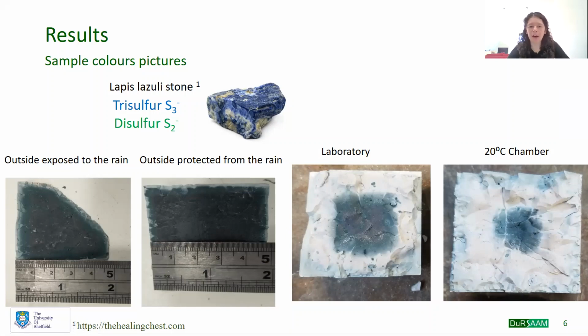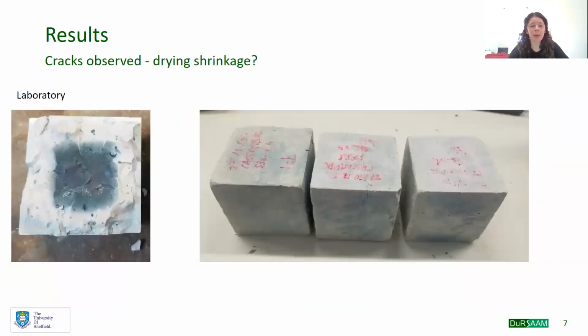It didn't go that far. This is mainly due to the relative humidity, which was really high outside and low inside. And also we had some cracks within the samples due to the drying shrinkage, due to the low relative humidity. So that's why the air was able to penetrate that far.